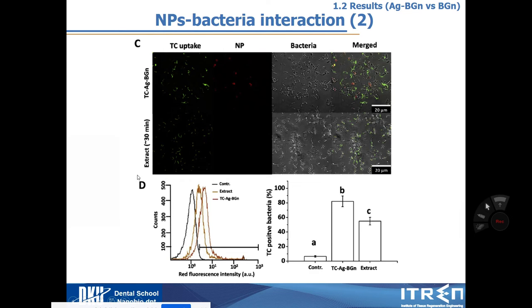This was quantified by FACS: around 80% of bacteria can take up tetracycline. But when you use the extract, which means without direct interaction between bacteria and nanoparticle, it is 60%. So we can expect a 30 or 40% increase of tetracycline uptake by the nanoparticle's direct interaction with bacteria.